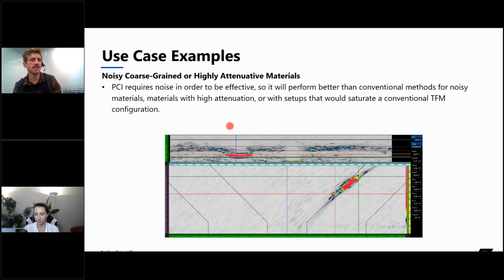So another use case where we're finding really good results with PCI compared to amplitude-based techniques is with noisy, coarse-grained, or highly attenuated materials. Like we mentioned a couple of times before, this is where PCI is really going to shine compared to conventional TFM or amplitude-based techniques, because we're going to have a better signal-to-noise ratio, because the contrast between the two is going to be much greater.